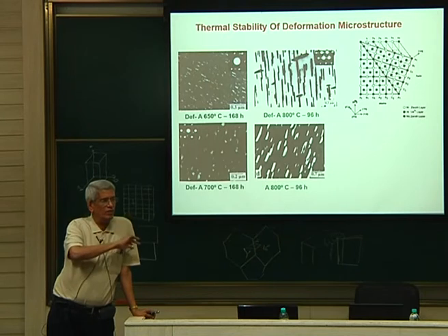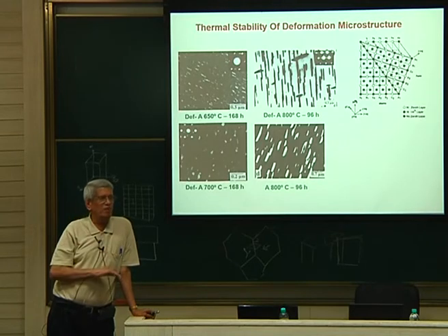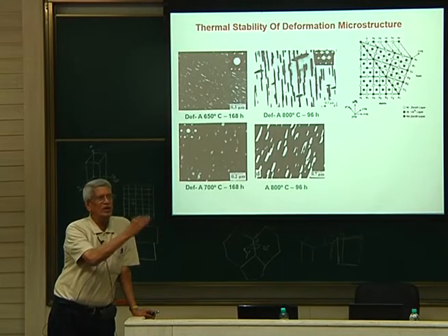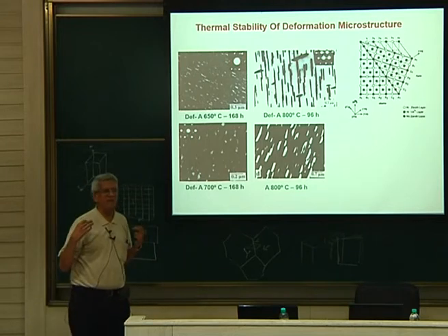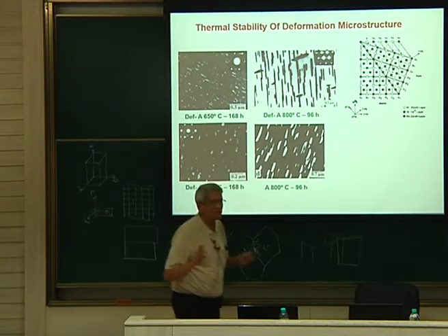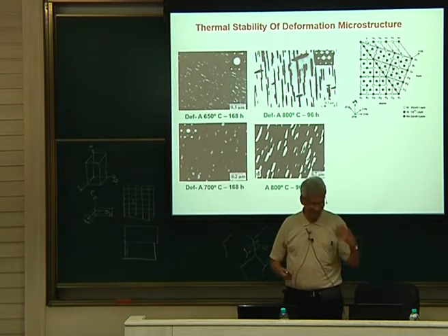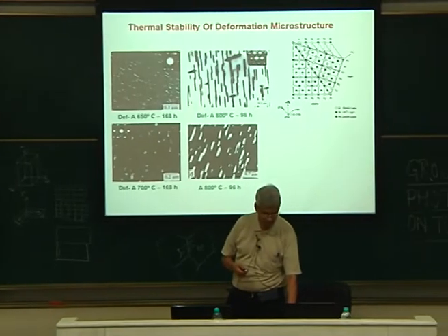Where the temperature is low, gamma double prime precipitates are there; where it has seen the high temperature, already the delta phase has started forming. In between they could see faulting and twinning. Okay. So this gives the satisfaction that what we have studied is quite useful to explain the microstructure which is seen in a structure which has seen very long time in service.